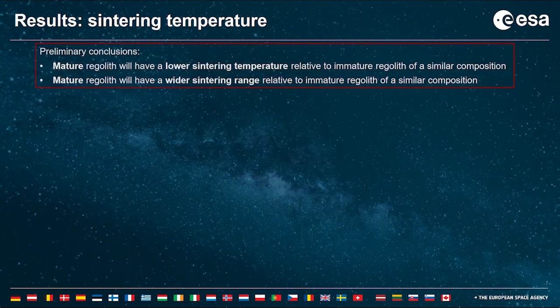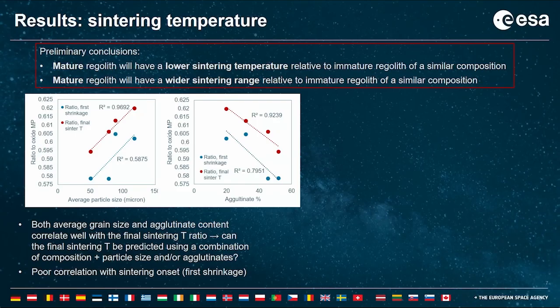So now to just hone in on the difference we see based on maturity. As I mentioned, maturity as a term represents a number of properties, and while some of these samples are designated mature or immature, they have different properties, and so we can look at that. So here is that data represented against average particle size in microns and against agglutinate content. And we can see that both of these things correlate quite well with the final sintering temperature ratio to what we would predict from the composition.